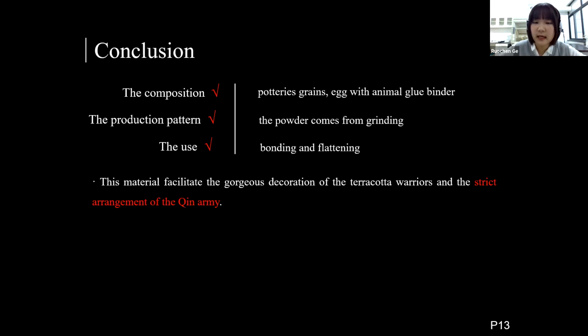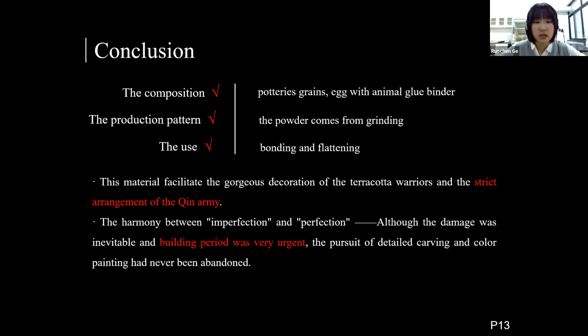So to achieve the integrity of the army and the high quantity of the statues, some statues that were broken in the process of the firing, for example, transportation and arrangement, were repaired with this material. Second, we believe that the building period of number one pit was very urgent. The time pressure drove the workers to repair the broken statues to finish the project rather than abandon them and